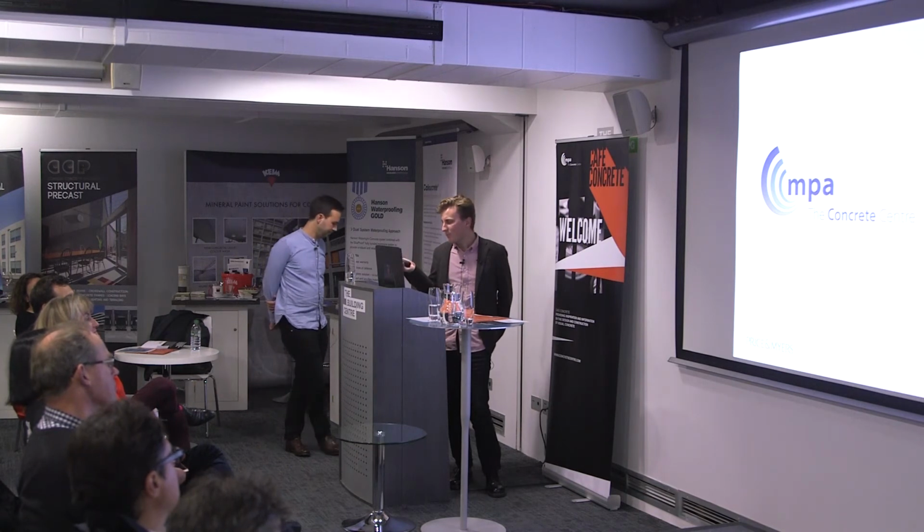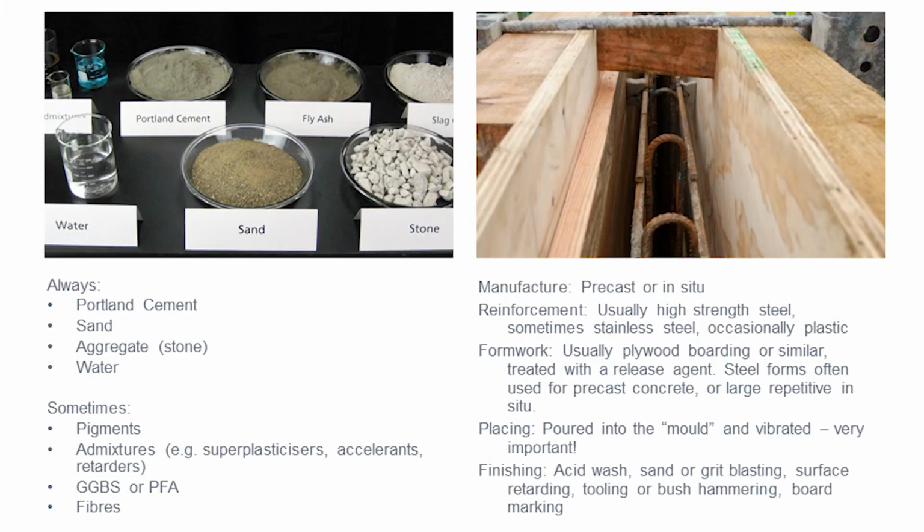On visual concrete projects, there's a huge amount that goes into that. You have your detailing of structural elements, everything about the formwork, release agents applied to the formwork, how you place and compact on site, how you allow it to cure, what the weather's doing, all of which are important to what you'll end up with in the finish. It's not just the engineer specifying a mix.